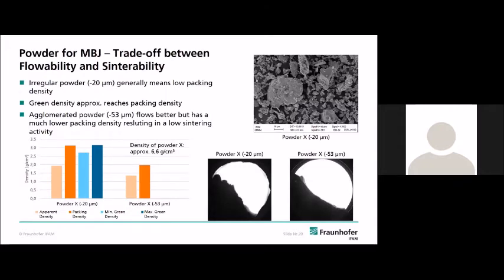If we look at the powder for metal binder jetting, we work with much finer powders compared to the beam-based processes. So we have mainly powders of MIM technologies or used in MIM technology. So we are working with powders below 20 microns. And there we always have a trade-off between flowability of the powder during the buildup of the powder bed and the sinterability. The finer the powder gets, the better it sinters together, so the higher the density of the parts will become, but the spreadability, the recoatability during the printing step might become a challenge.